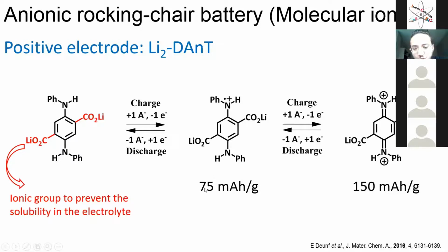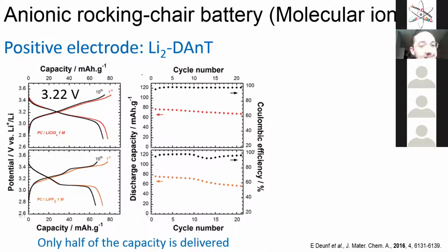For one electron, you reach a capacity of 75 milliampere hour per gram. And then if you add a second electron, you will reach a capacity of 150 milliampere hour per gram, which is not bad actually, with the potential of this molecule. So in practice, on the left is the galvanostatic charge-discharge of this molecule. It reacts at an average potential of 3.22 volts, which is pretty good. But the capacity is a little bit lower. It's 75 milliampere hour, so this one is limited to one electron.